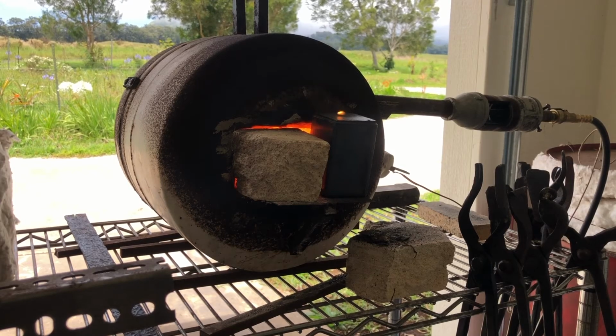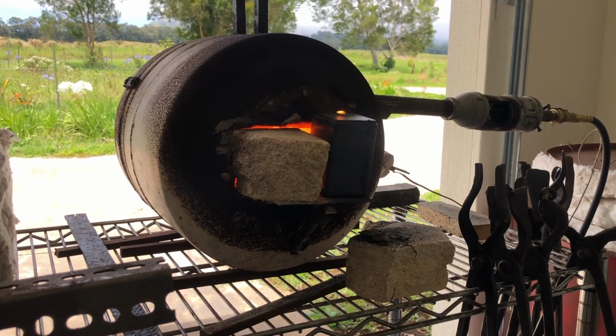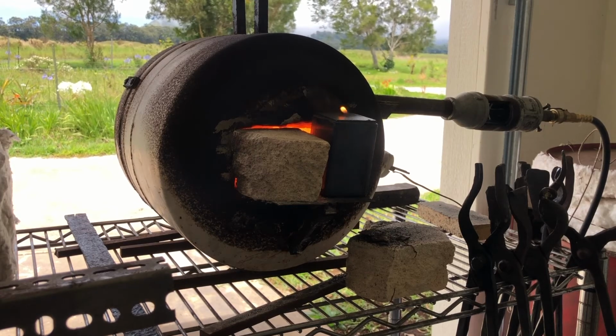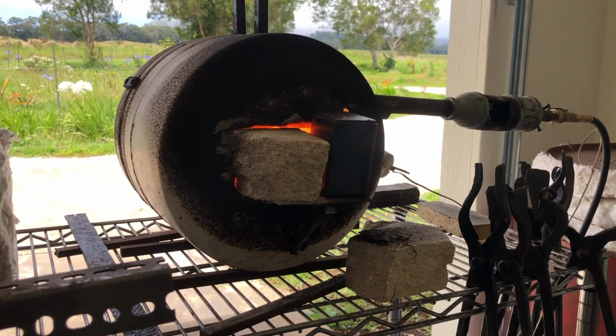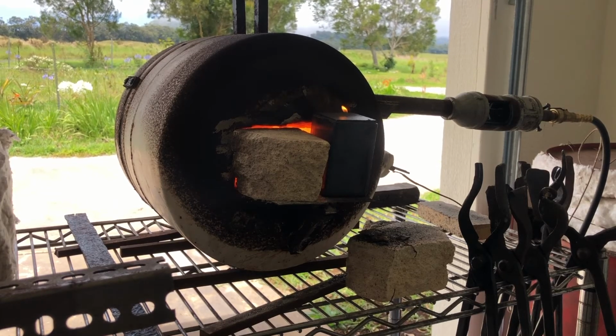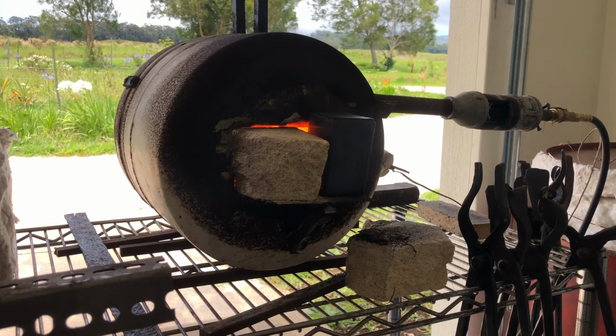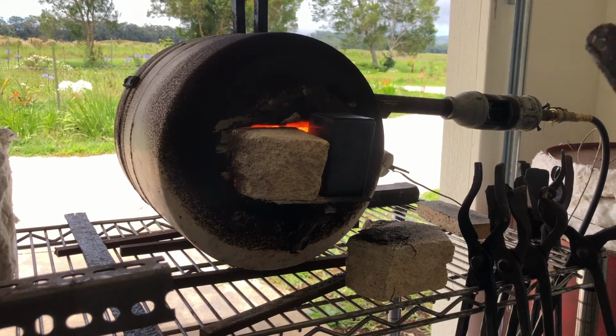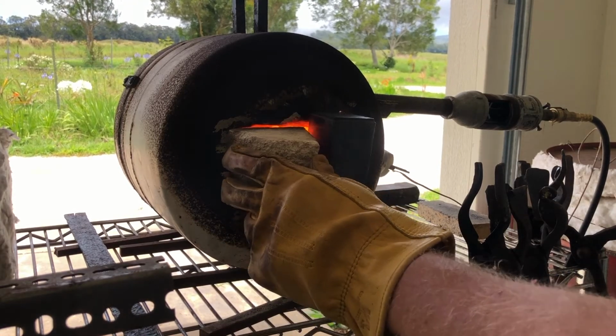See, I'm getting just a little bit of flame as the heat penetrates into the center of the block. So there was obviously just a little bit of methyl cellulose left in there. I do expect that this baking off has also probably left a little bit of carbon residue in there, a bit of soot, and any of that that doesn't burn off will just get incorporated into the steel. We've got basically no flame there at this point. Every once in a while, a tiny flicker.